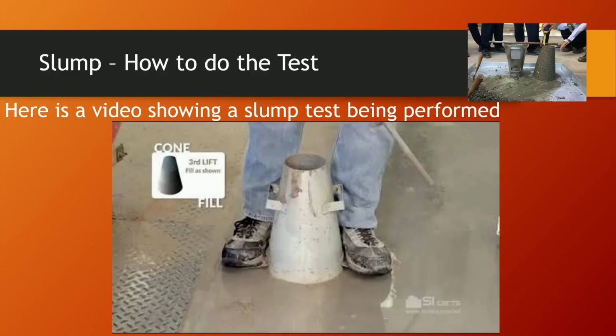First thing you want to do is make sure that your slump cone is moist both inside and out. You want to perform this test on a flat, smooth, rigid surface, free of any vibration. Typically, your agency is going to bring out a piece of poly and throw down. The cone will be held in place. You can stand on the ears or you can use the slump plate and lock them into place.